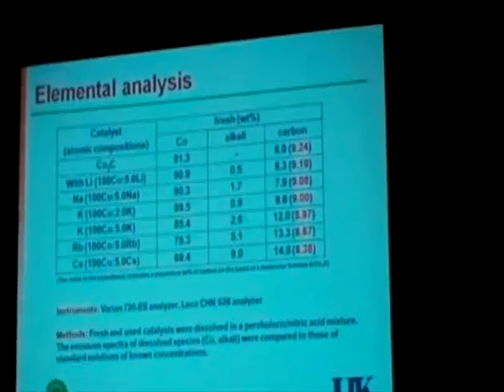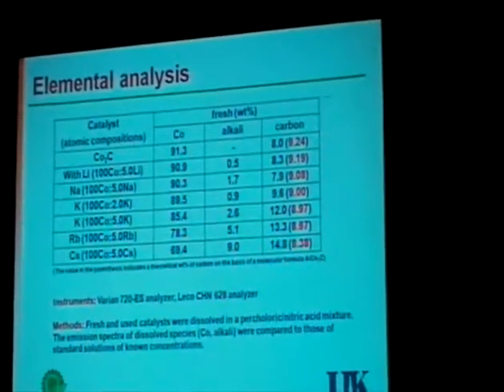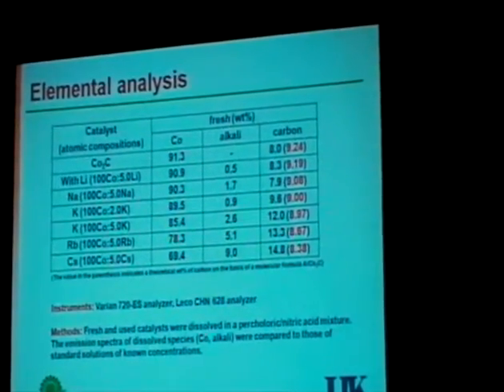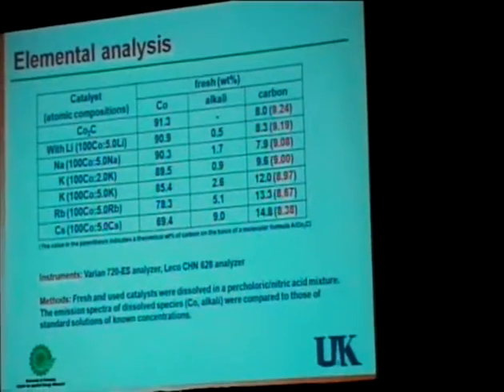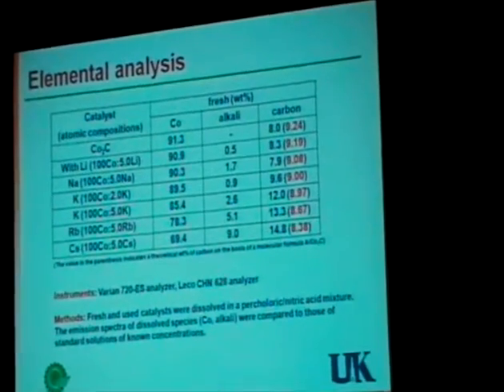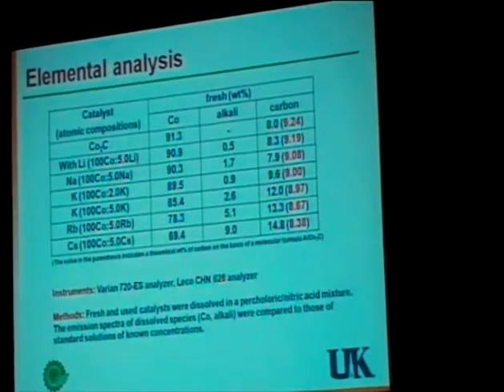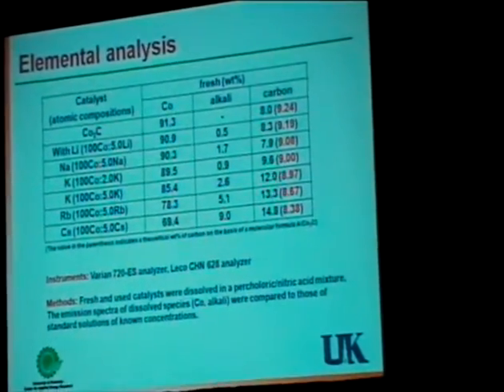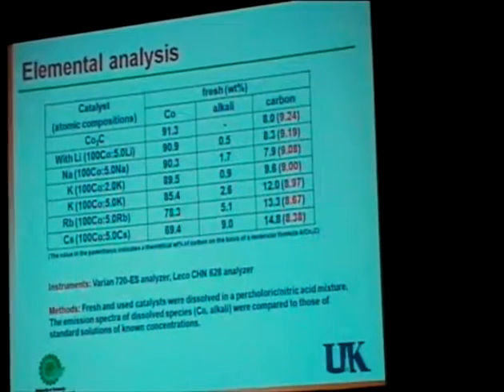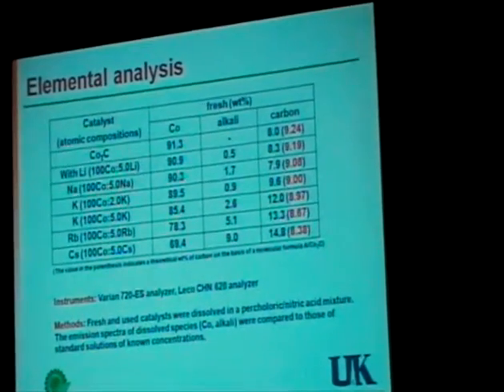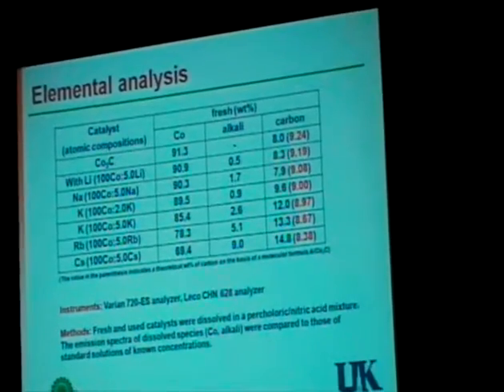So the method that we use for the elemental analysis, as well as the instrument, was an ICP-OES analyzer and then a CHN analyzer to analyze the carbon content. The fresh and used catalyst were dissolved in a perchloric/nitric acid mixture, and the emission spectrum of dissolved species was compared to those of the standard solution.